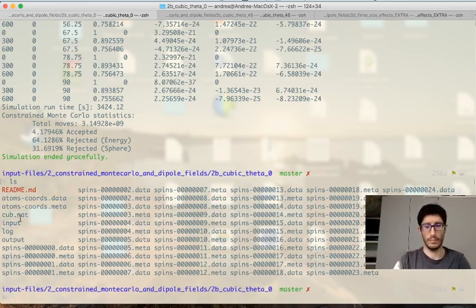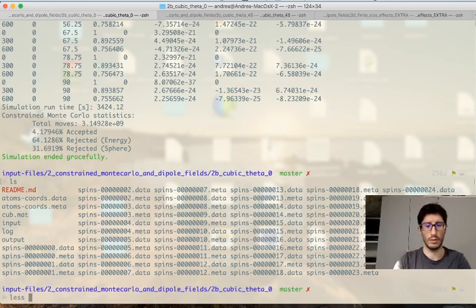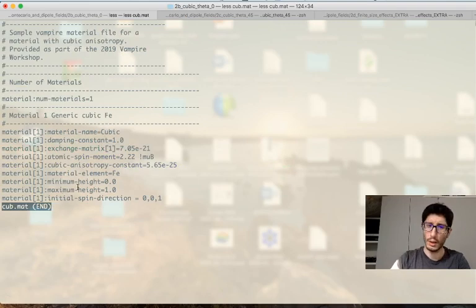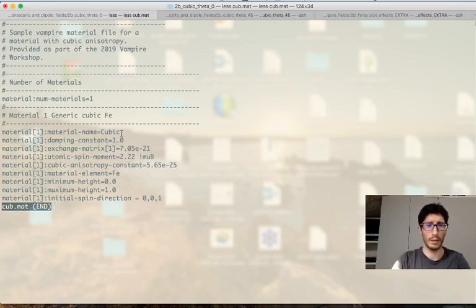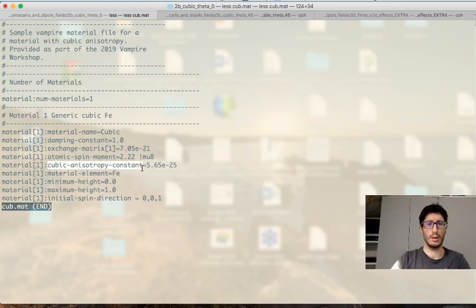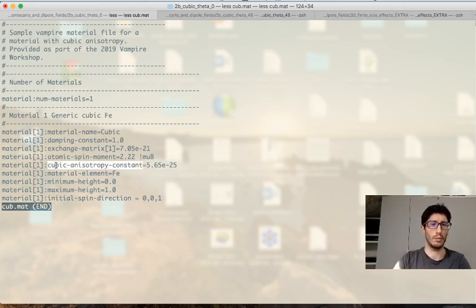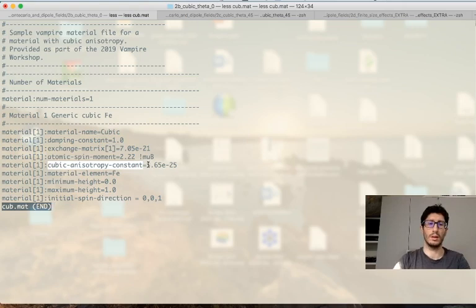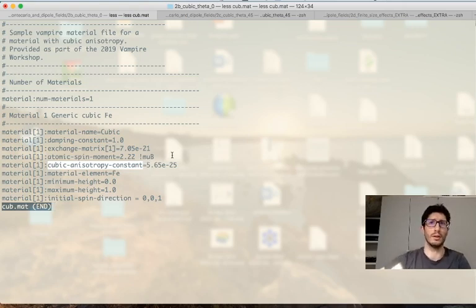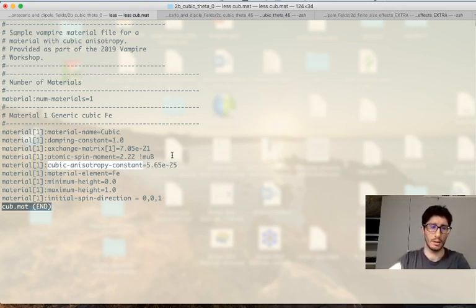The cubic material file we can just have a very quick look. It's this iron-like material where the important segment is this one we require to have a cubic anisotropy constant and because the sign here is positive this will set the anisotropy to be along one of the three major directions. If it had been minus then would have been along the diagonals.